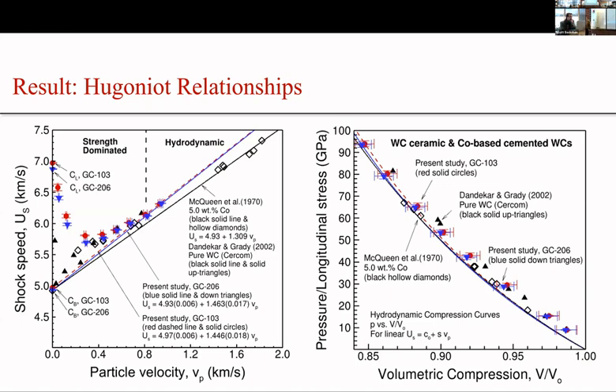The data points on the left of the figure fall into the category of the strength-dominated region, which means at this point the shear stress carried by the sample is still comparable to the pressure, so the strength is dominating the shock behavior. That is why the measured shock speed is more towards the longitudinal sound speed instead of the bulk sound speed when the particle velocity is very low. As the stress level goes to a very high level and reaches the hydrodynamic equilibrium state, the shear stress almost goes to zero. That's why when we extrapolate the data points, we intersect the y-axis at the bulk sound speed as the particle velocity goes to zero.